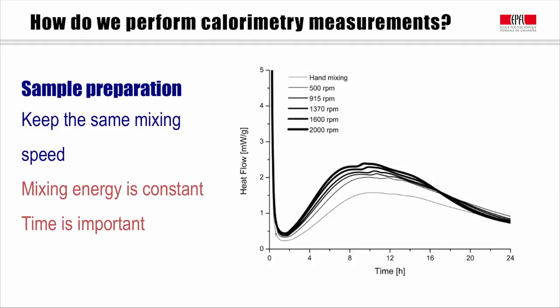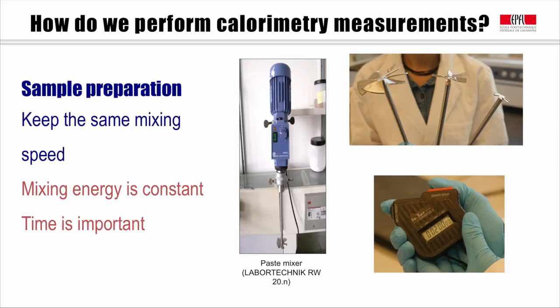Before casting, we need to prepare a mixer, a suitable stirring pedal for different sample sizes, and a stopwatch. In our protocol, we use mixing speed of 1600 rpm and the mixing time is 2 minutes.